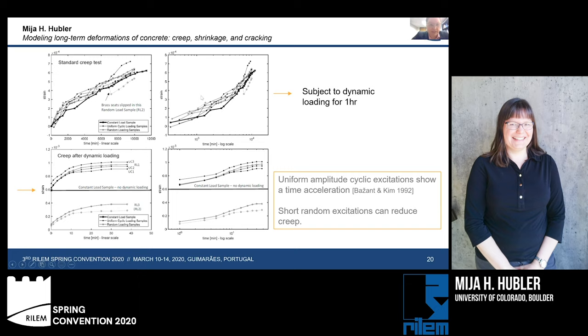After the initial creep test, we subject it to either an hour of the uniform cyclic loading or the random loading. Then we conduct another creep test. And this is what we observe for all the uniform cyclic loading cases, UC1 through 3, that there is an acceleration of the creep beyond this horizontal line that represents the samples which were not exposed to any dynamic loading. However, for our random loading, we find that in fact, for some cases, we see a deceleration. So the response of the creep is below this line where we have no dynamic loading.